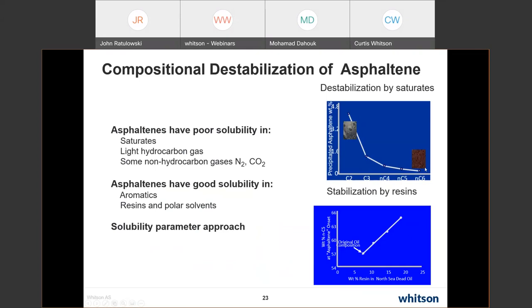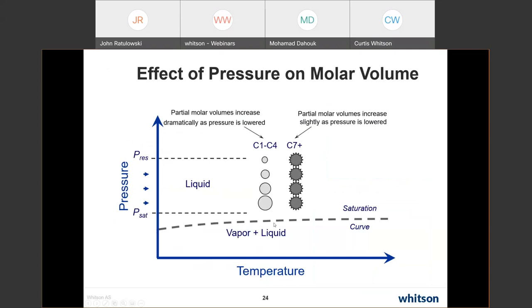All right, I put this up because a lot of people have a hard time saying, you know, compositionally, nothing is changing when I depressurize. The composition remains the same. Why does the asphaltene solubility change? And this is just a little cartoon that makes it, at least for me, easier to understand. These light gas components, as I decrease pressure, their partial molar volume increases quite substantially. On the liquid components, the C7 plus components, as I reduce pressure, their partial molar volume doesn't increase that much. It does increase a little bit, but not a lot.